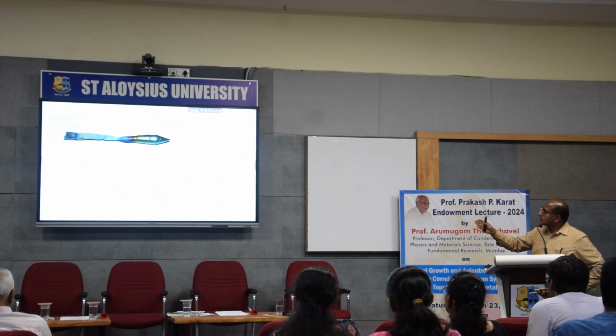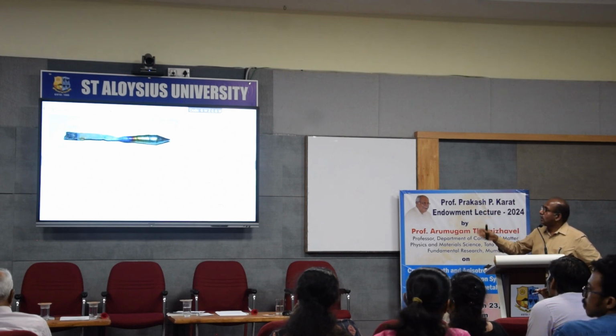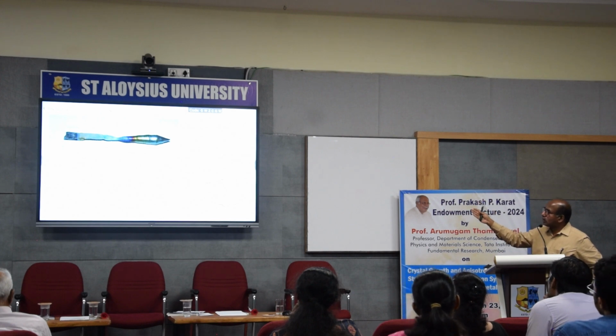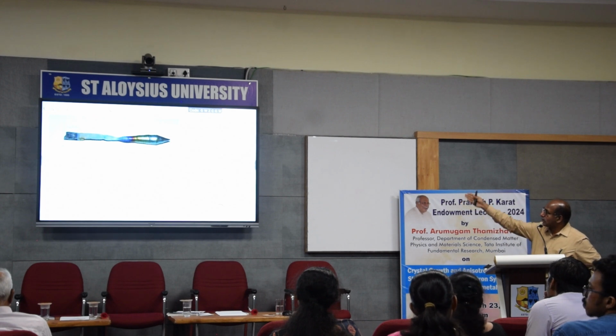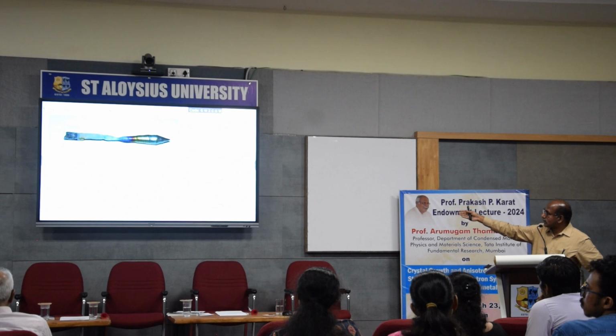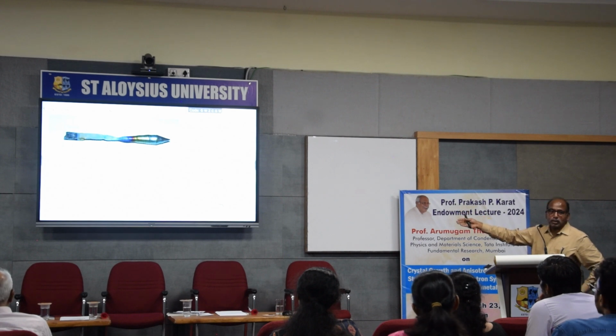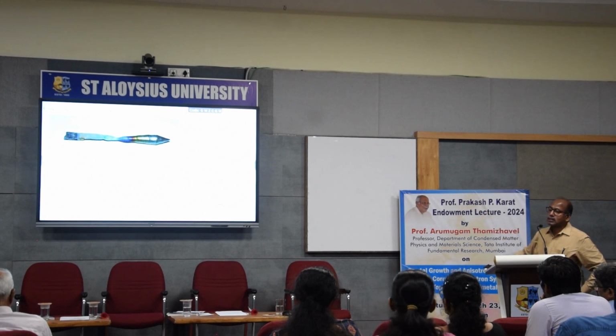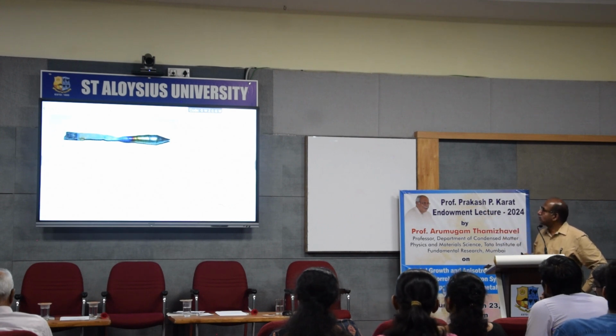This is a sample which exhibits superconductivity at around 5.7 Kelvin. It also shows another kind of transition called the charge density wave transition at a higher temperature, around 74 Kelvin. And you can see the anisotropy. If I pass the current along the A axis, the resistivity is about 200 microohm centimeter, and along the C axis it's about 50 microohm centimeter. To study these kinds of anisotropic properties, these single crystals are highly useful.